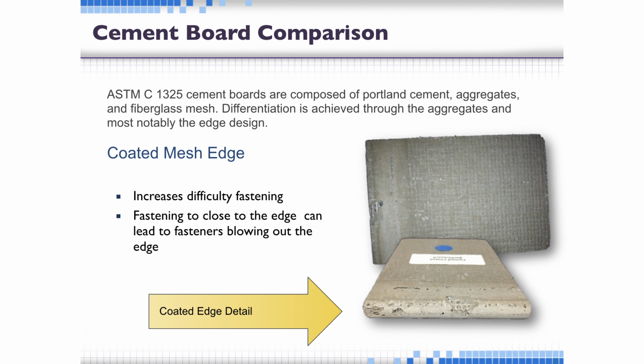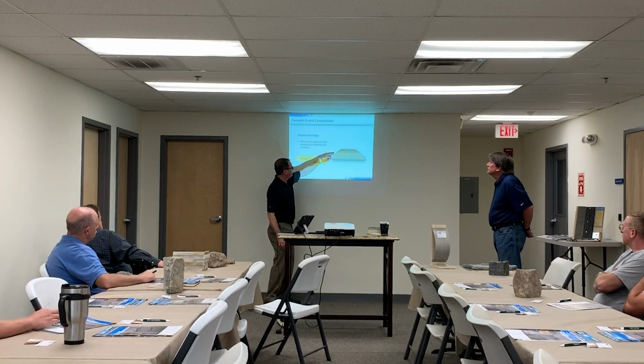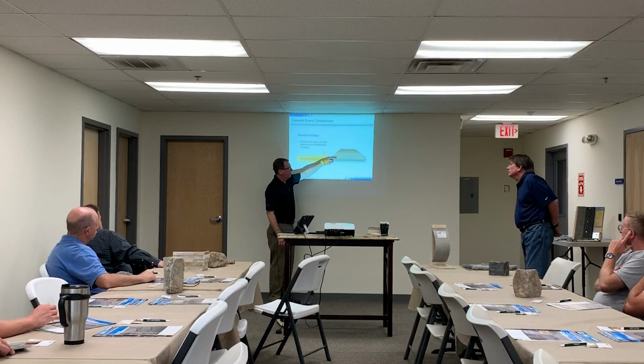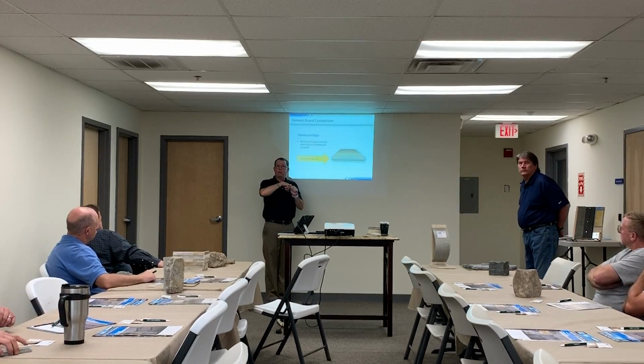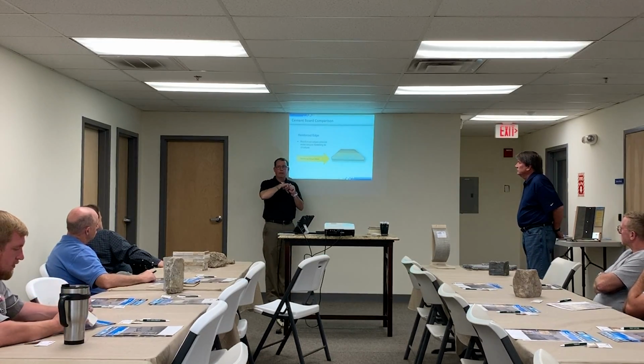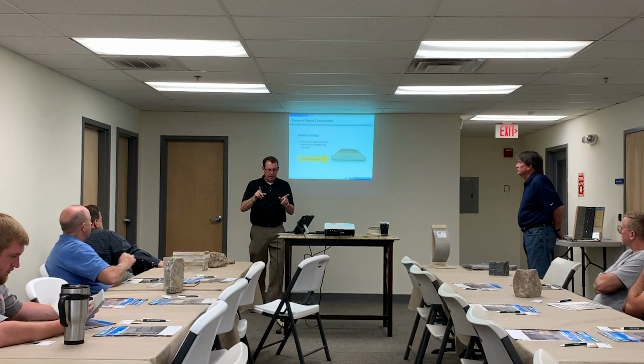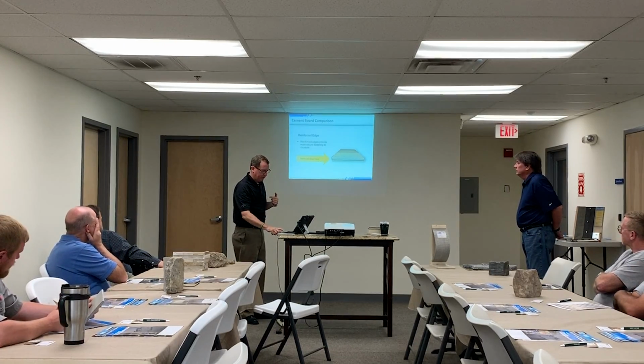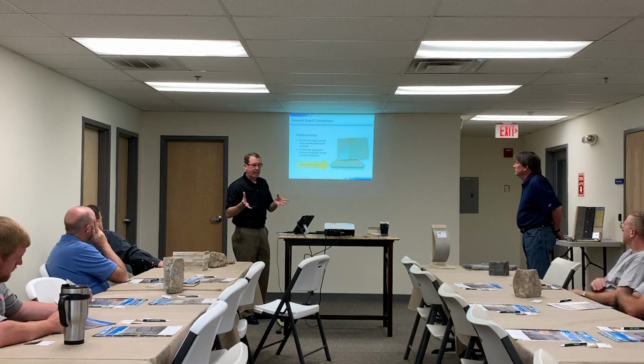So what USG did with Durock is they actually came up with a nice coated edge, and now they actually put a fabric on their edge. So this fabric will hold the fastener a lot better. You can actually pinch it. So if you have to toenail your screw or your nail into the stud, you can actually do that and still have holding power with it. So that was the big advantage of that. And then PermaBase, which is our product from National Gypsum, was actually the original one that came out with that.